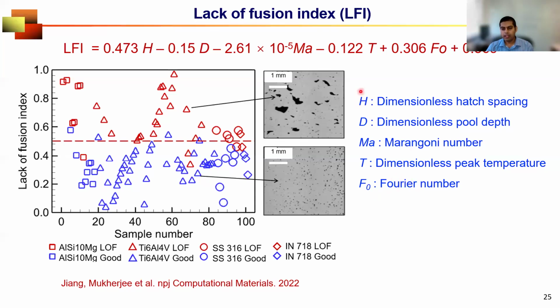Now, if you have all these variables somehow calculated using an additive manufacturing model, we can even get a linear regression model and propose an index that can delineate between the porosity cases and cases where the porosity is very less. So that's the advantage of combining modeling and machine learning, to identify very important scientific insights to be able to solve such a complex problem like porosity defect in additive manufacturing.